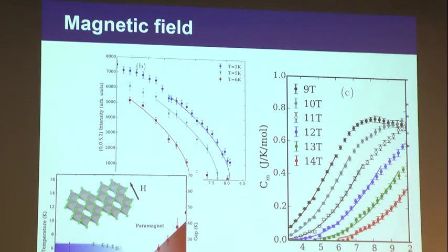You might have noticed that this is really exciting, and if you remember the original Kitaev slide that I showed you, the really interesting phase in the Kitaev model is when you have a magnetic field in the isotropic limit, where you have non-abelian anyons that you can use for topological quantum computing. So is that really it? Is this the gapped phase that you introduce by applying a magnetic field in the Kitaev model? Unfortunately, that's not the case, because for that to materialize, you want to apply the magnetic field along the direction perpendicular to the honeycomb plane. But in this case, we are applying the magnetic field in the honeycomb plane. So that's not exactly what's happening.